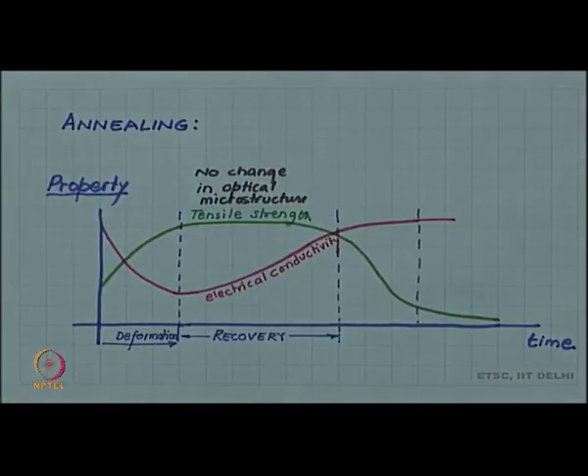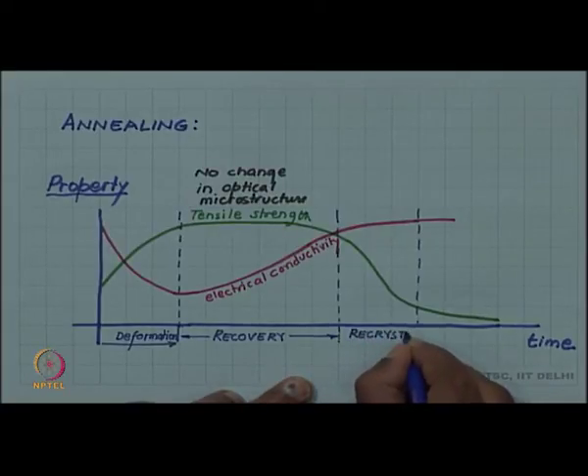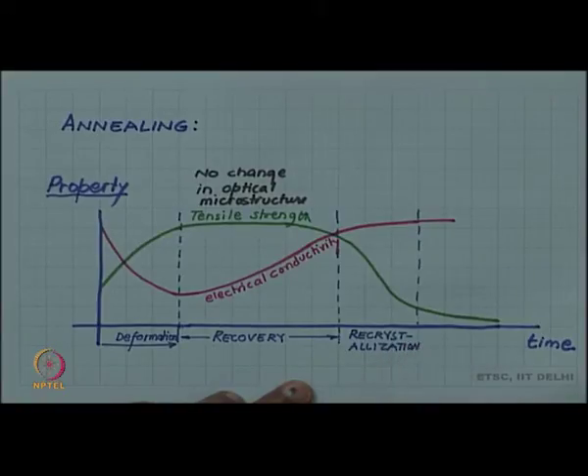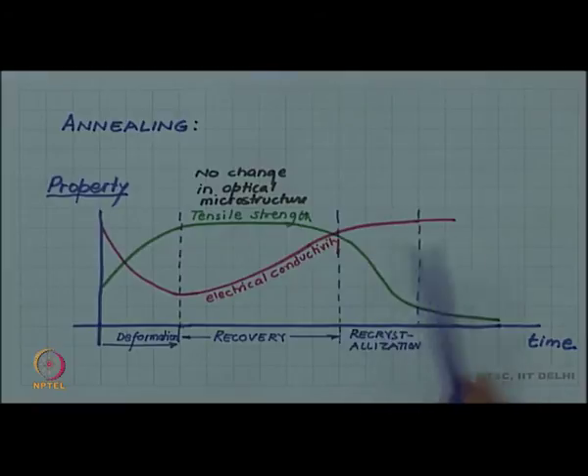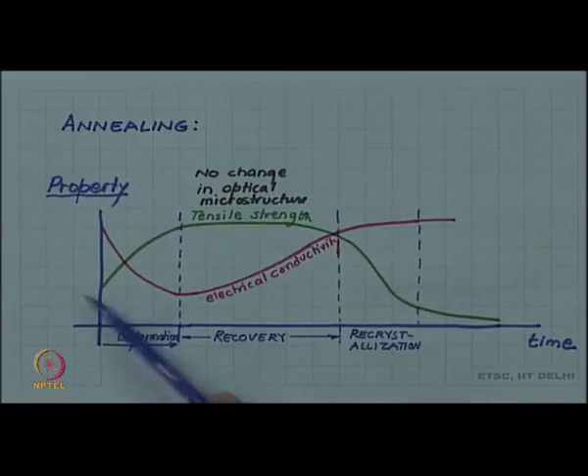After recovery, there is a second stage called recrystallization. During recrystallization, electrical conductivity gradually increases, but there is a sharp decrease in tensile strength to its value equal to or less than that prior to deformation.